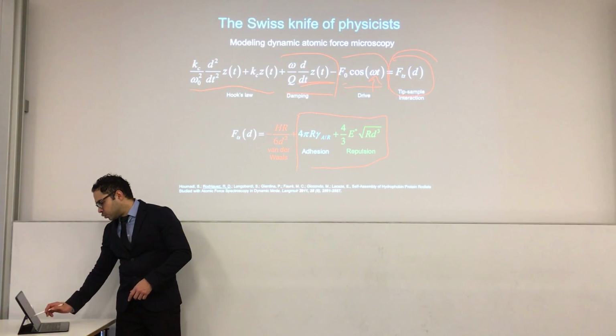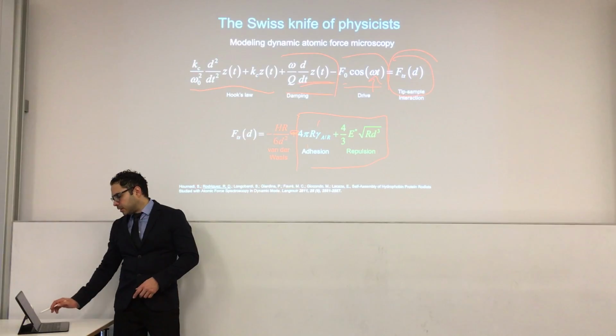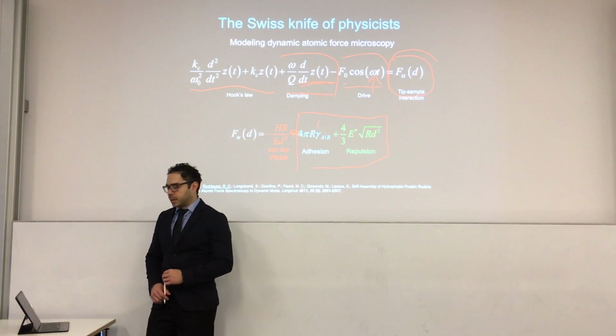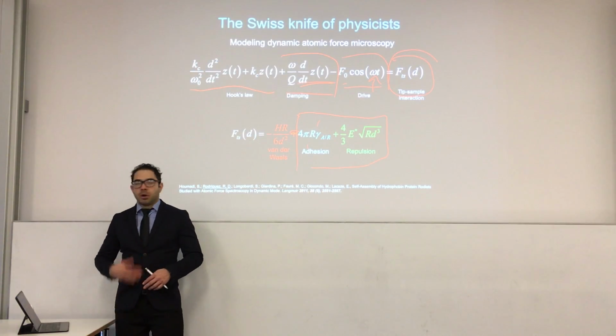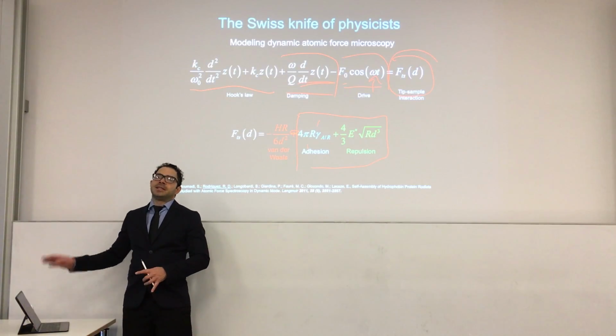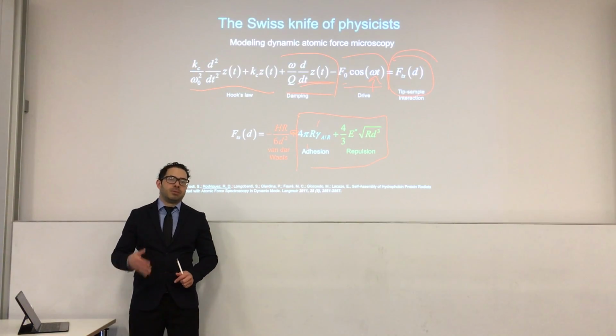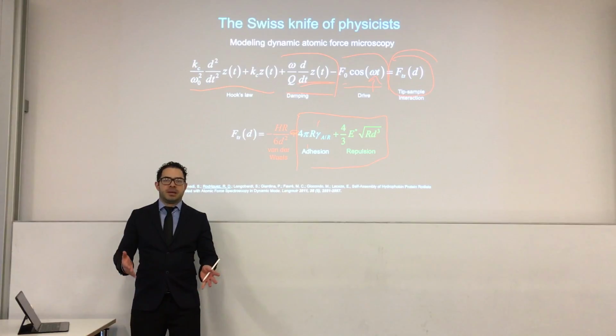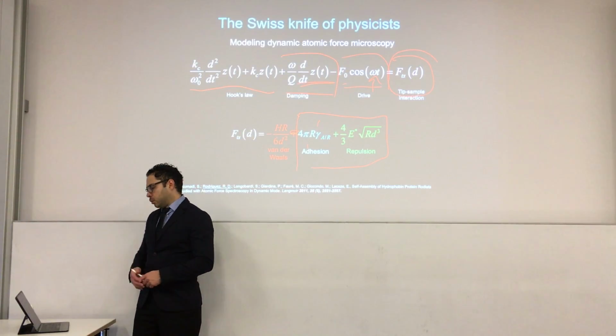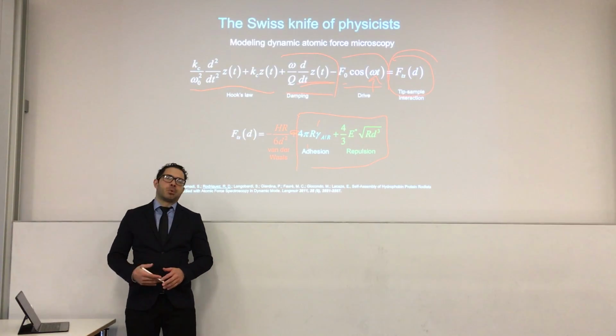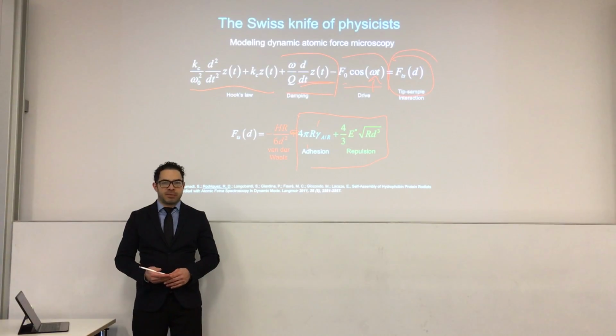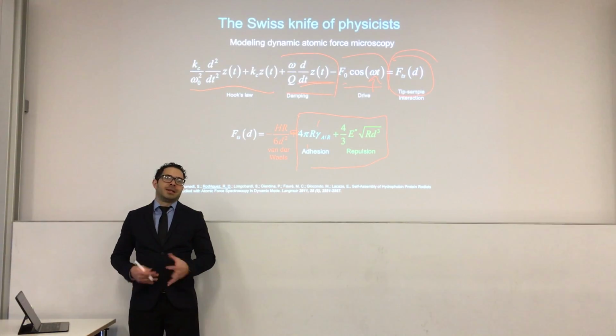This adhesion force is actually negative at the end because the surface energy is negative. So here you will have an attractive force. You have an attractive force and a repulsive force in the contact regime. There are other forces that I don't mention here, but already this simplistic model can allow you to model your tip-sample system in a very good way. However, if you want a more realistic approach, you also need to consider capillary forces, for example, or electrostatic forces.